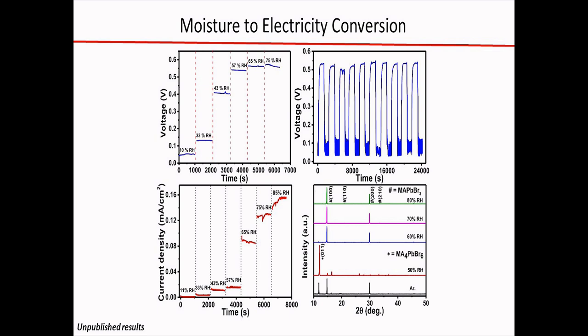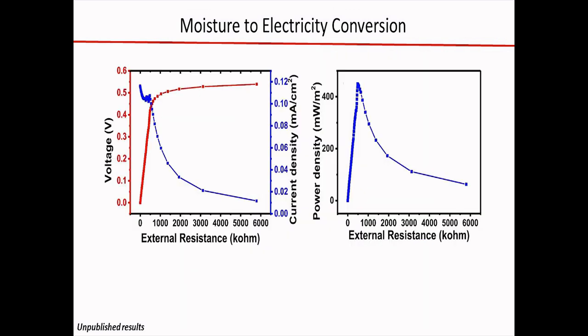And we also carried out the XRD, which shows the transformation from the 0-dimensional perovskite to the 3-dimensional perovskite, which is a transformation that is completely reversible.